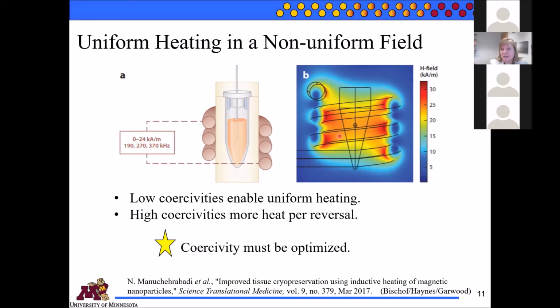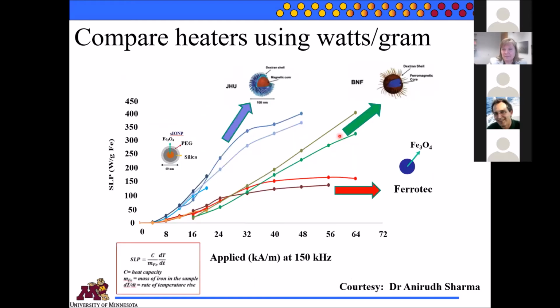Because right now, the higher field you apply for nanoparticles, the more heating you get. And that's because you keep circling the hysteresis loop, more and more area of that loop. So coercivity needs to be optimized if you want to have uniform heating in a non-uniform magnetic field. Here are the results.